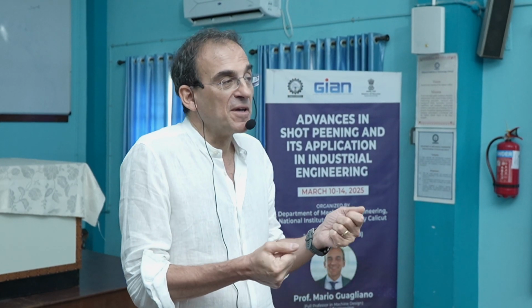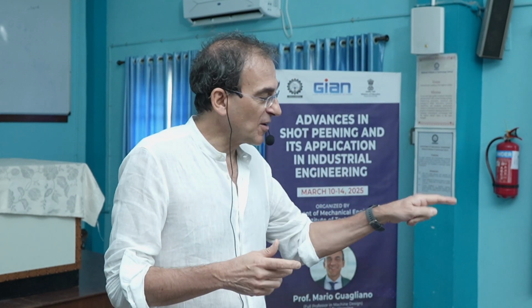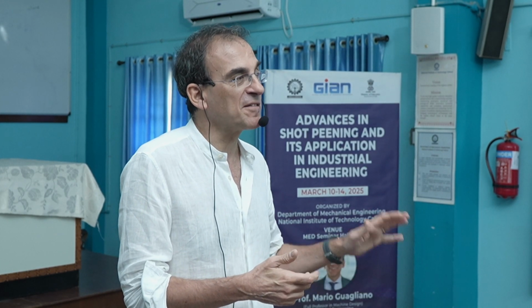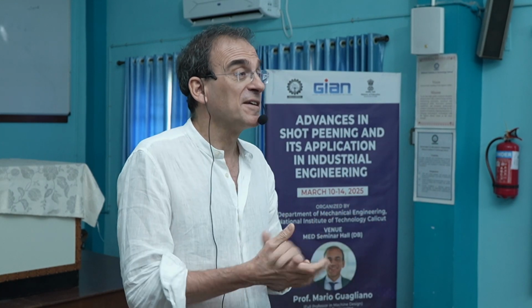And I don't know if you have noticed that in any of the papers I have shown, there is any residual stress measurement. They are not considered. Why? Because indeed the nature of the shot peened material is different, and the residual stresses that will be generated will not be the same. We need something that is going to harden, non-uniform plastic deformation, and in the case of polymer this is much less relevant, let's say.